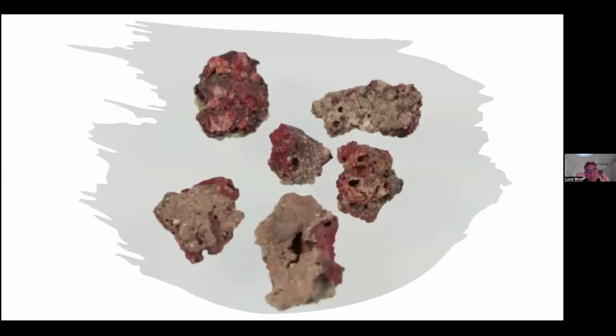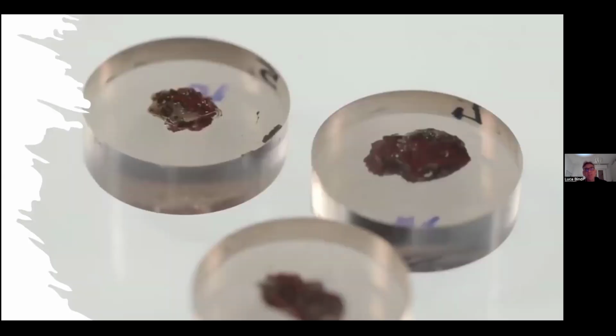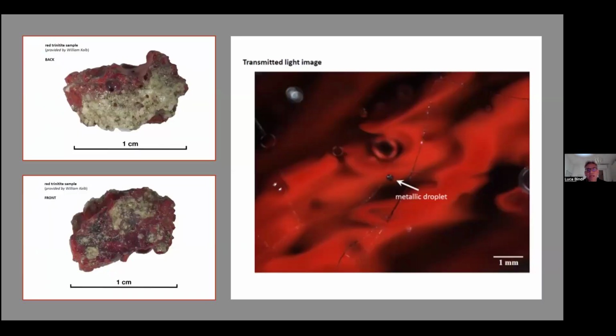I studied several red trinitites by putting them in epoxy and polishing the surface and studying the internal structure, just to see the possible presence of metallic droplets or something like this. And look at this. This is a very interesting red trinitite sample. So look at the high resolution image on the left, and look at this transmitted light image where you can see these small metallic droplets reported here. You can see the red color due to the presence of copper in the silicate glass.